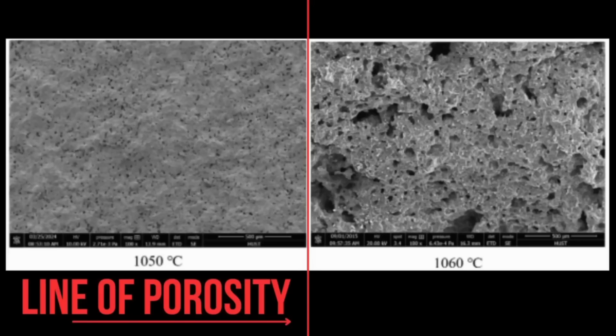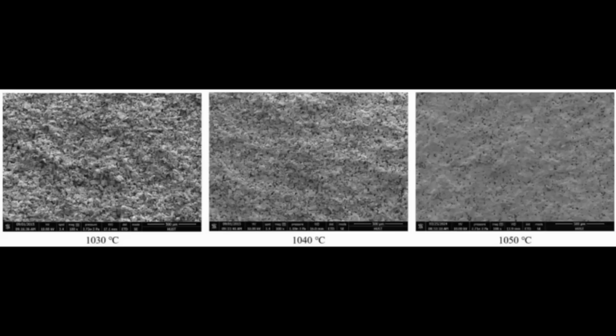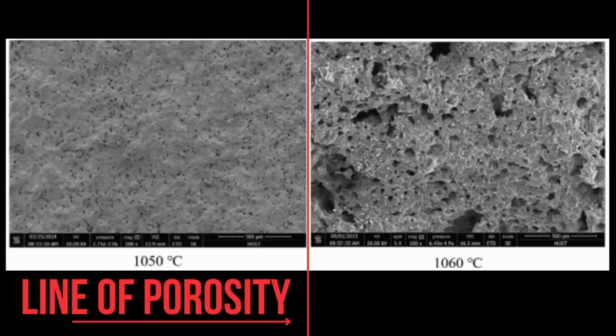So it turns out the key to a really good sinter lies in getting as close to the line as possible. Let's call this the line of porosity, and approaching but not crossing it will give the highest fused particles with the lowest amount of pores. Since this line of porosity appears to be somewhere around 1060 degrees, it explains why the regolith sintered at precisely 1050 degrees had the best properties in the study, as it got very close to that edge, but didn't cross it.